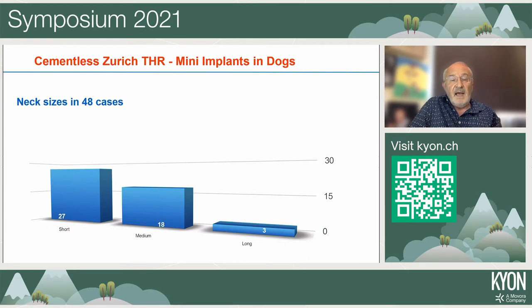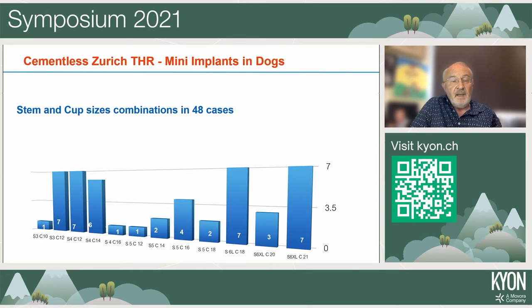For the neck size, we always tend to use short, maximum medium. So we had only 3 cases where we needed to use a long neck. But if you provide the proper cut of the osteotomy, not too deep, most of the time you will end up with a short or a medium neck. There are combinations between the stem and the cup.